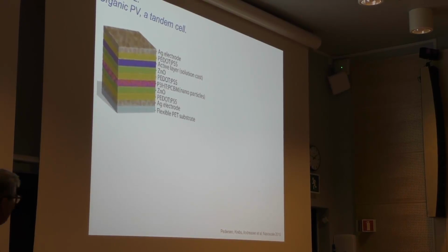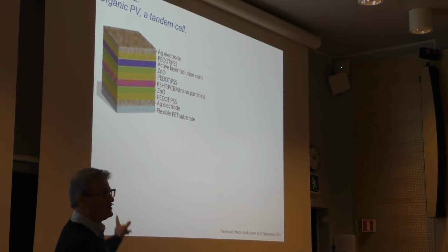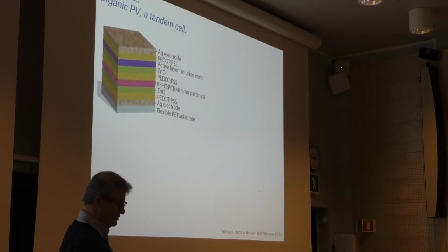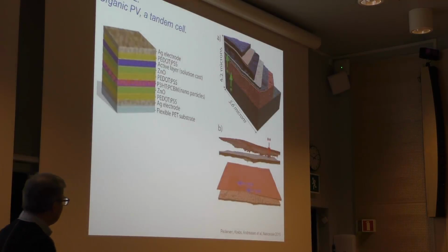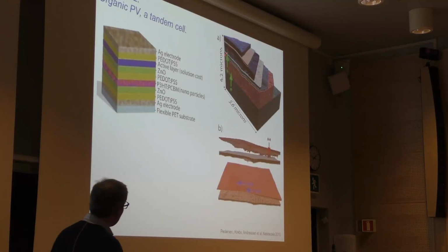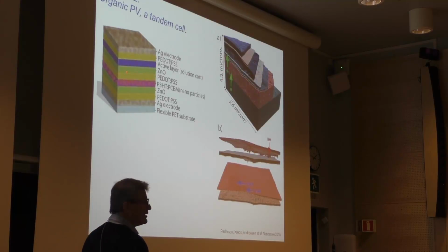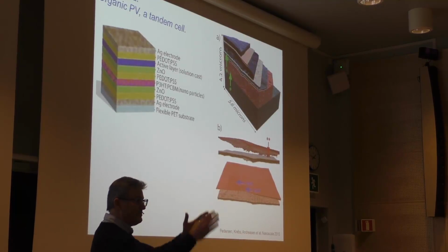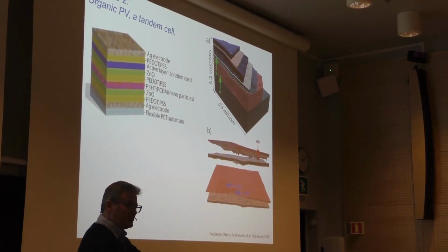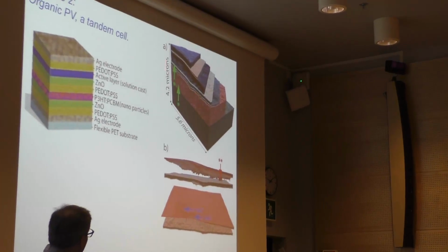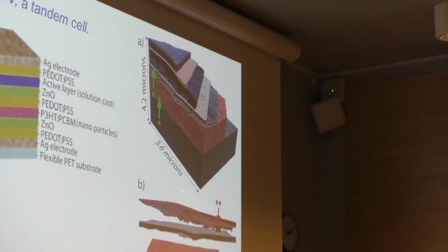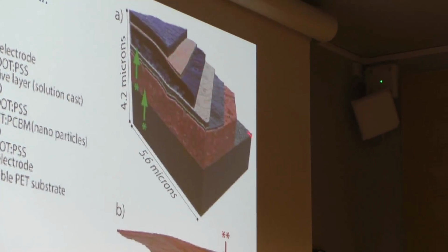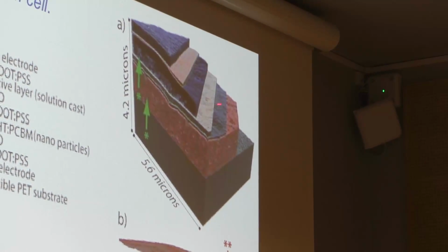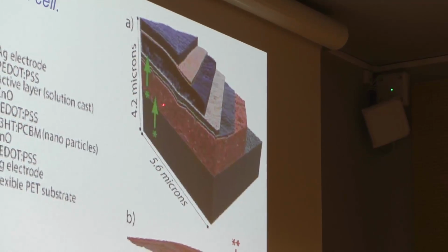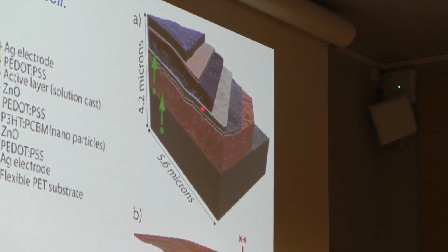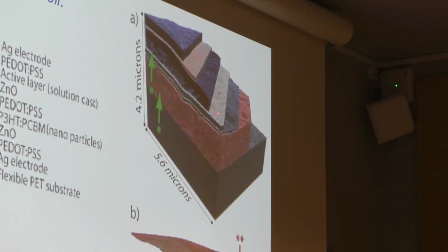So what we have here is a technique that we can use to actually look at these layers. So here is what we got. What we did was that we had a stack like this. We used a FIB, focused ion beam, to cut this into a prism-shaped thing, like you can see here. These cuts are artificially made numerically afterwards, but you can clearly see that we are able to distinguish these different layers, right?